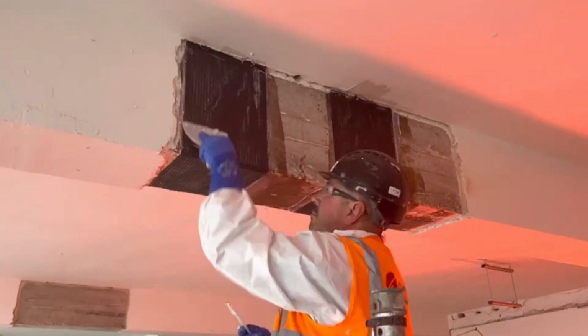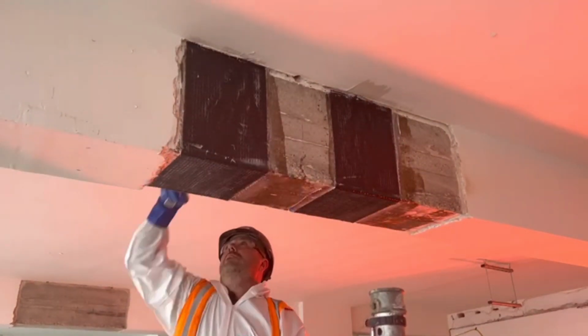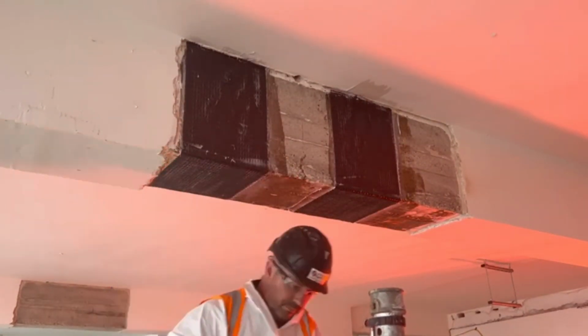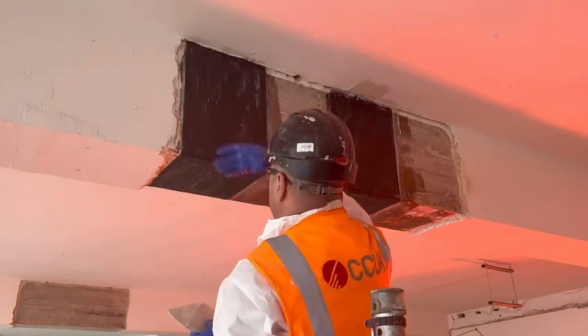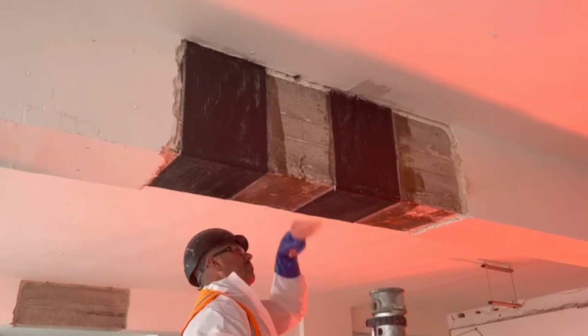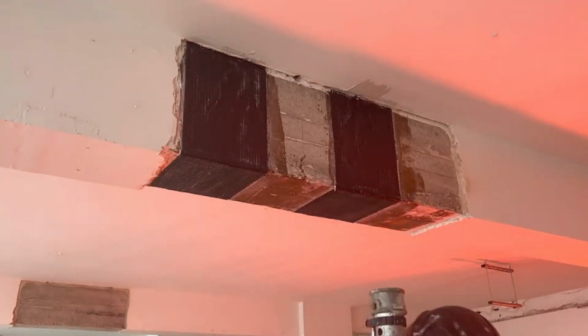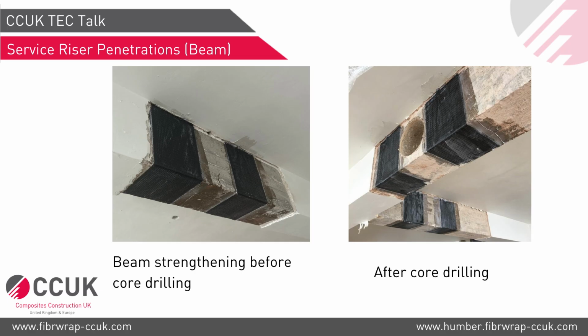So once the process is complete, how long is it before the contractor can come back and actually core drill the beam? Yeah, so in ambient condition, the FRP will be 100% cured in 72 hours. So they can come back in 3 to 4 days time and core this opening.